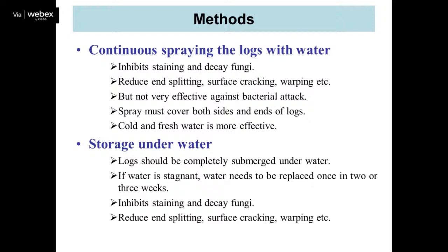Then there is the storage of logs in a pond. When we are storing logs in the pond, it is very important that the water should be replaced once in 2 or 3 weeks. It protects the wood from certain microorganisms. When water saturated conditions are there, it becomes very difficult for decaying organisms like fungi to grow, because the amount of air present in the wood goes down, and then the fungal growth also reduces. It prevents end splitting, surface checking and warping.